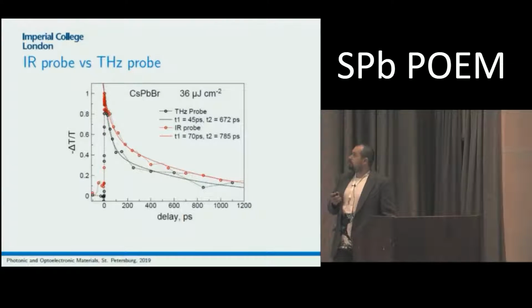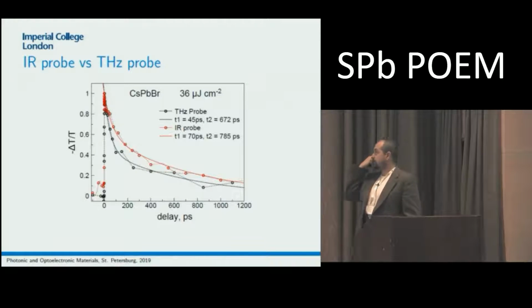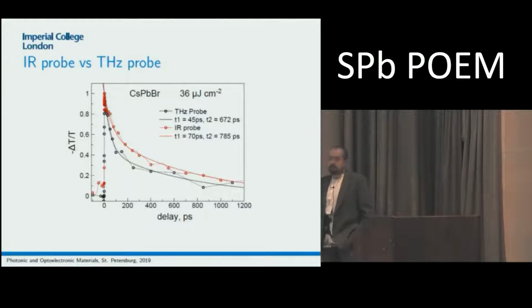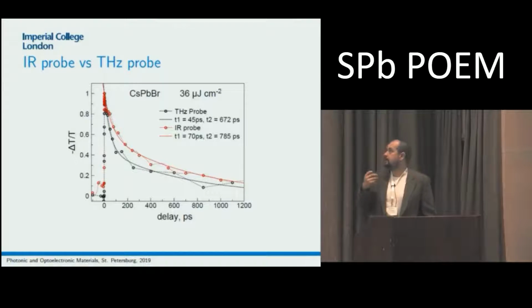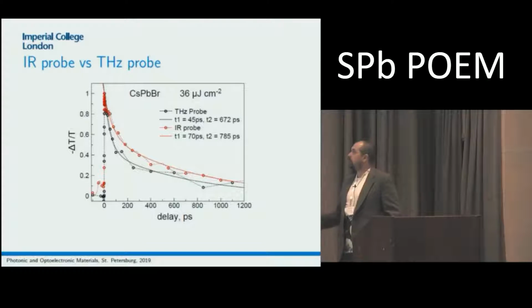Indeed, these are results for cesium-lead bromide perovskite. This is an inorganic perovskite, and it's not as efficient as the previously mentioned benchmark MAPI, but it still gives some decent efficiency and gives some decent signal in both pump probes and terahertz.